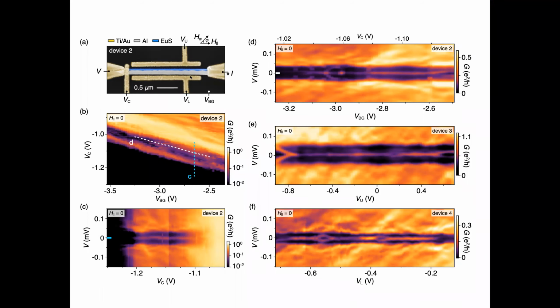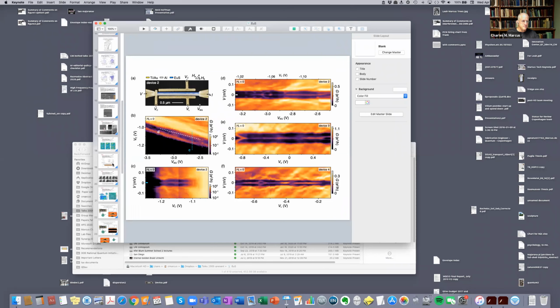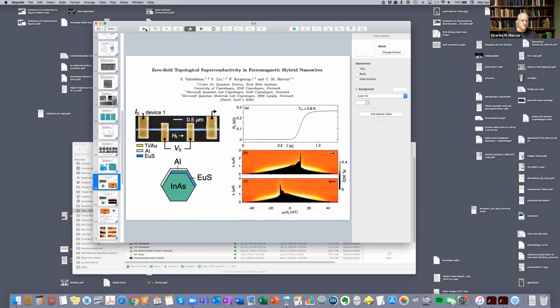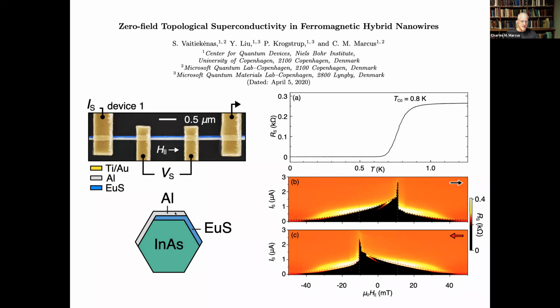Yeah, I think that I understand this. I don't think that it's that, which isn't to say that I know what it is. I think that what's happening is that if I go back to what the structure looks like, this picture, the structure is fragile in the sense that the europium sulfide has to induce a nearly killing amount of spin splitting in the aluminum in order to drive those states to zero. So there's almost not enough Zeeman field to bring them to zero.